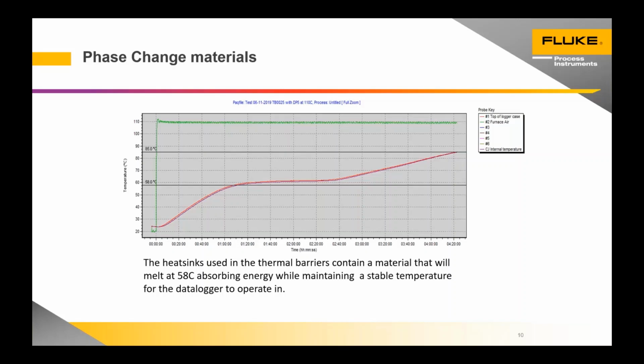The red one is showing the data logger. And you can see that in the first hour and 10 minutes, the logger raises from room temperature to 58 degrees. Then the phase change material starts to melt. And the heat energy coming into the system is essentially staying the same. The furnace is at 110 degrees.